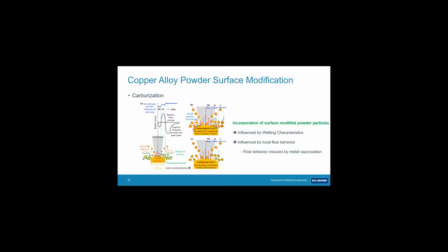So we believe that for the carbon decorated powders, due to these forces acting on these powder particles, we lose the decorated carbon and we basically suck in pure copper chromium powder again, which does not contribute at all to an enhanced absorption. While if we carburize the powder, the carburized layer stays there because we could still find back carbides after laser powder bed fusion. And we think that basically you suck decorated powder particles in your melt pool, which effectively contribute to the enhanced absorption.